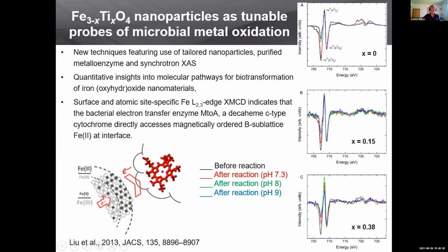So using that combination of XRD for the bulk and then XMCD for the surface, we used this solid solution series of nanoparticles as tunable probes of microbial metal oxidation. And to do that, we isolated this enzyme, MtoA, which is a decaheme c-type cytochrome, and we exposed that to these iron-bearing minerals that had different solid iron 2-3 ratios, and demonstrated that the c-type cytochrome could directly oxidize metal from the ordered B sublattice of the magnetite minerals at the surface.